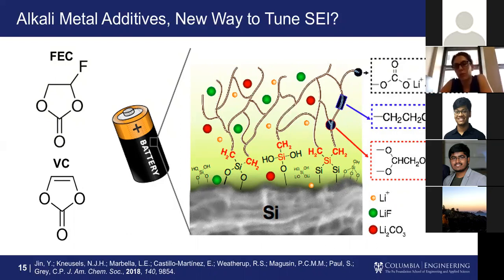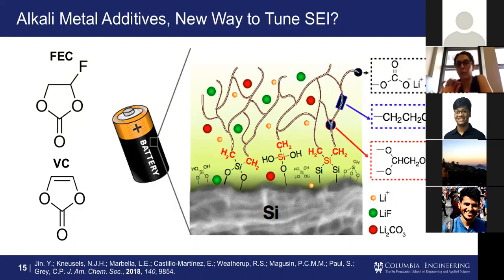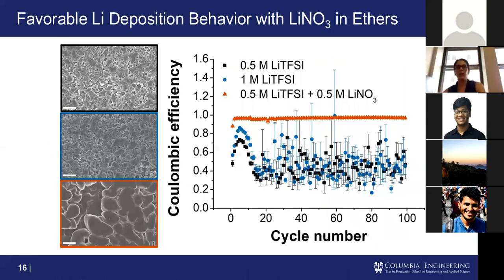Supposedly, these branch chain polymers offer better mechanical properties in the SEI, and this is a very active field of study. But what our work is showing us is that these alkali metal additives might be a completely new way to tune the SEI. So instead of adding something to the SEI, we're intentionally taking it away. We're not forming lithium carbonate, and we're not forming these soluble alkyl carbonates that seem to be detrimental for lithium ion battery performance. So that was very fun and interesting to us.